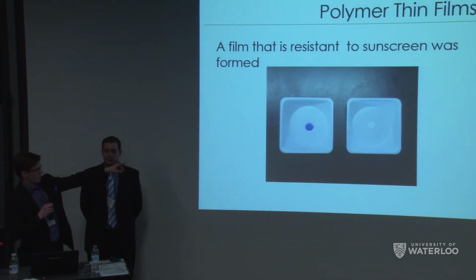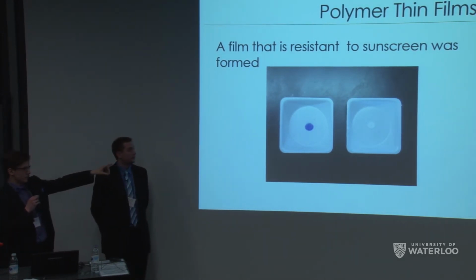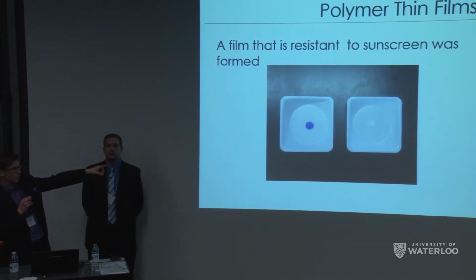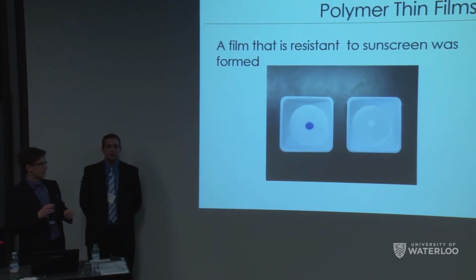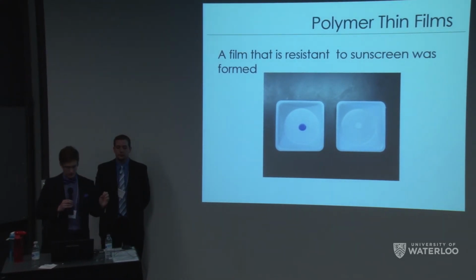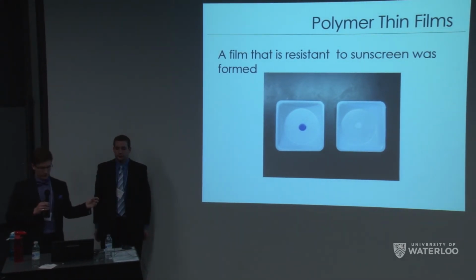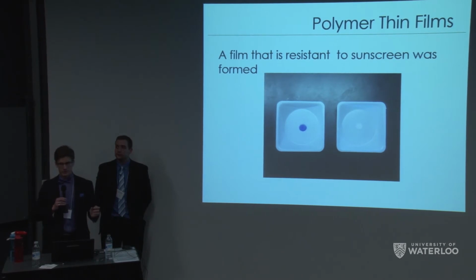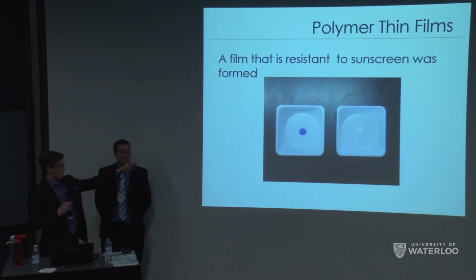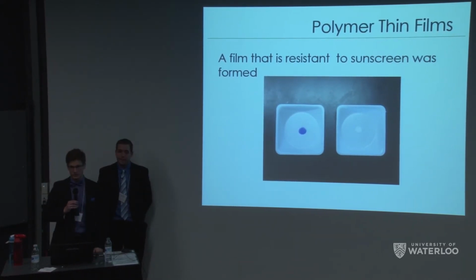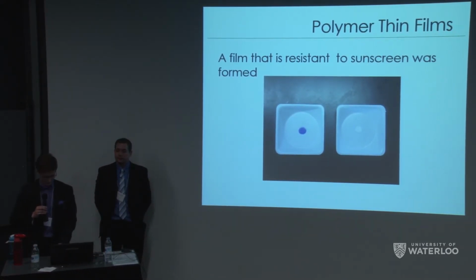So on the right, although it's harder to see because sunscreen is also white and the tray is white, we've applied sunscreen over top of our ink. And on the left is just the polymer, our film forming ink drawn on a tray. And we exposed both of these trays to about 10 seconds of UV light. And you can see that instantly, the one on the left tells you exactly when you're exposed to UV light, and then the one on the right shows that not only did the ink not smear, but that sunscreen is protecting the ink, and our ink remains in its clear or whitish state.